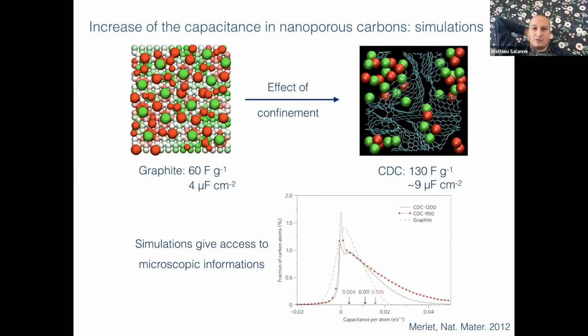And the advantage, of course, of simulations over experiments is that we have access to microscopic information. And so in that case, what we showed is that, in fact, in this nanoporous carbon, the increase of capacitance is mostly due to the fact that you have some highly charged carbon atoms. In graphite, we have a Gaussian distribution of charges, while when you start to go towards complex carbon structures, you start to have a very skewed distribution. And this corresponds to carbon which is only in contact with anions or cations on both sides of the surface. These are highly charged, and so you have a very strong effect of the confinement.